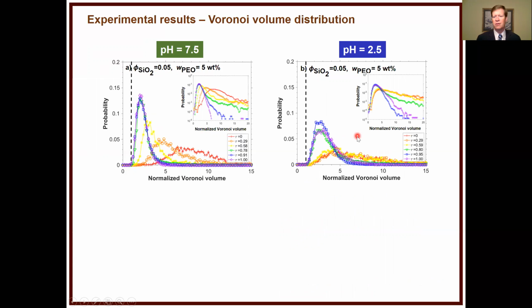At pH 2.5, we see something very different. What's different is initially, in fact, the gel structure is more compact, the microstructure in general. That's because you have particles that are touching, and then particles that are very far away from each other, and very open voids that are sliced up into these weird pie shapes, if you know much about Voronoi polyhedra. But what you can see is all of these, even though it's flowing and changing and evolving, all of these distributions are the same until eventually they break and snap into a new configuration. And this is what I meant by a gradual chemical process versus a sudden drastic mechanical process.